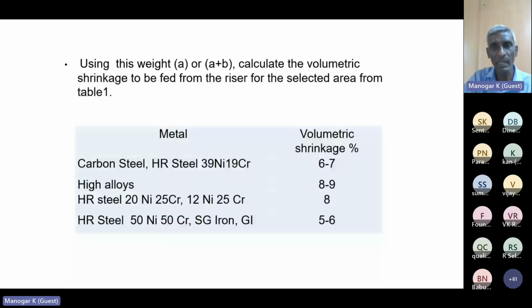Using this weight, calculate the volumetric shrinkage to be fed from the riser for the selected area. The volumetric shrinkage varies depending upon the alloys you are going to cast. These are some of the examples given: carbon steel 6 to 7%, heat resistant steel with different chemistry, and cast iron. Even though they say cast iron has expansion, for heavier sections we have to consider risers.